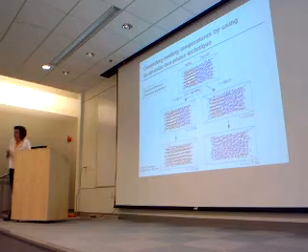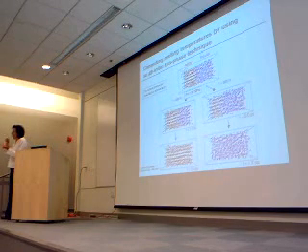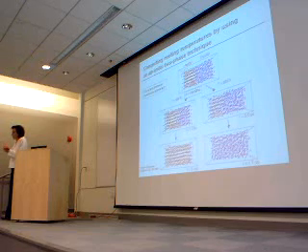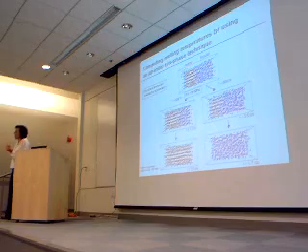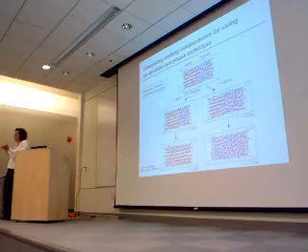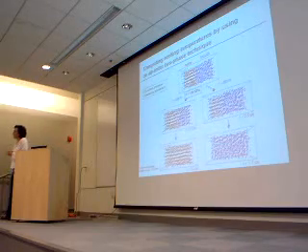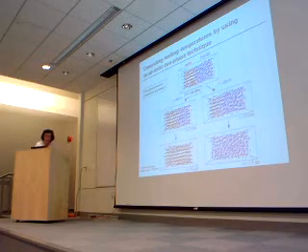So you have to have a set of criteria: diffusion coefficient, g(r), and in some other cases, some other electronic properties we were looking at, or other transport properties. So you use a set of criteria that consistently tell you whether the system is a liquid or a solid.